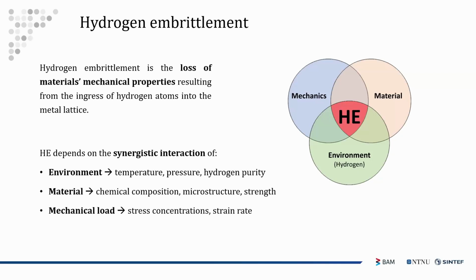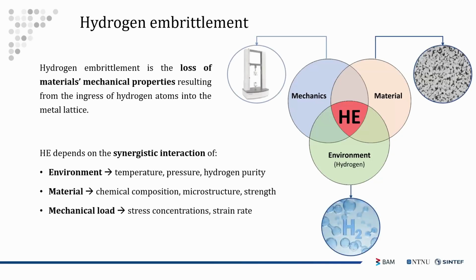We need a susceptible material. So the material could be susceptible or not based on its chemical composition, microstructure, and also strength, but also the presence of internal defects. And finally, the presence of mechanical load. In this case, considering that we tested with slow strain rate tensile test, we consider the strain rate, but also the presence of stress concentration that could result from notches or pre-existing defects. All these parameters are crucial for the material susceptibility to hydrogen embrittlement. So they should all be thoroughly evaluated when it comes to, let's say, evaluating the suitability of an existing infrastructure for hydrogen transport and storage.